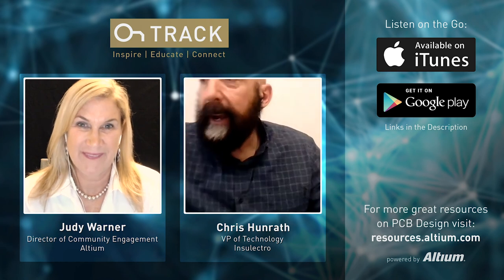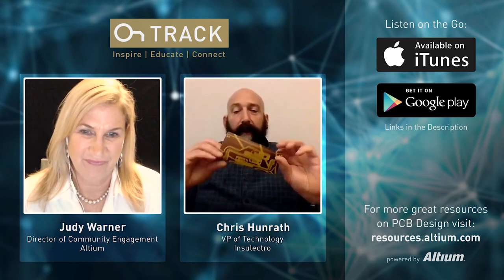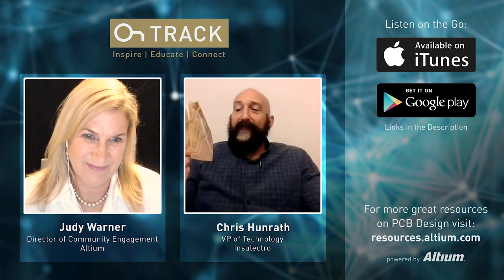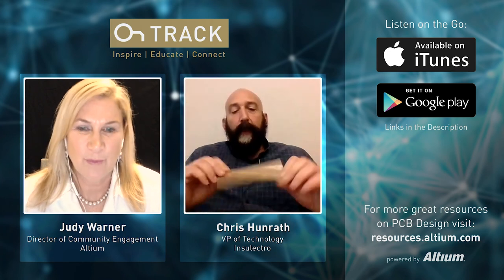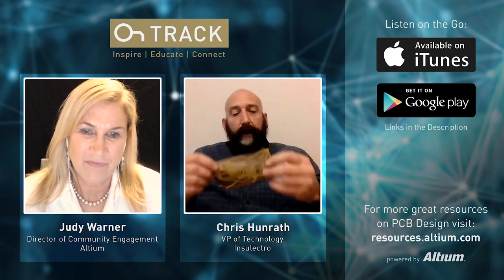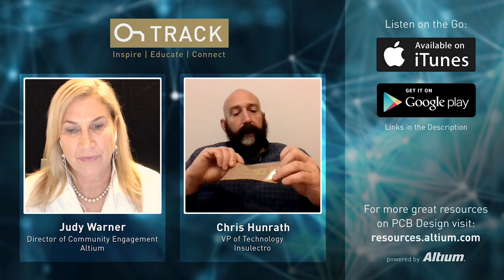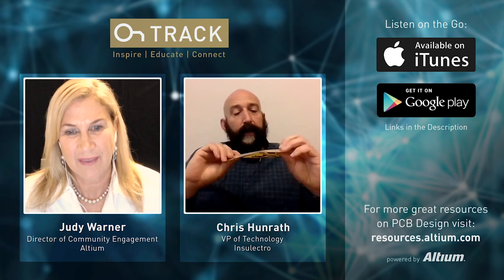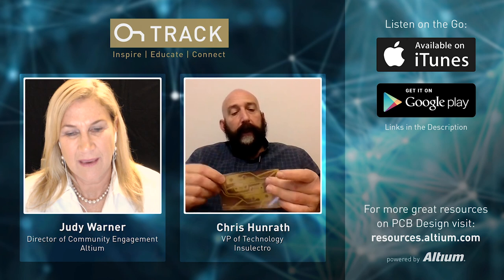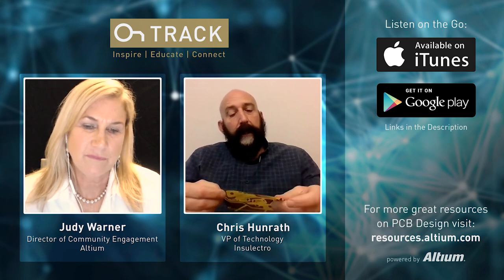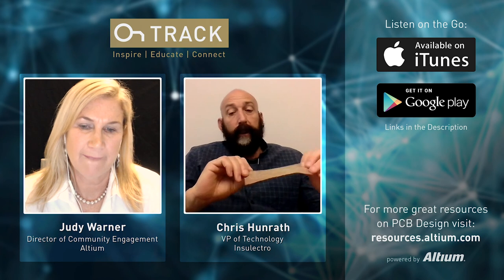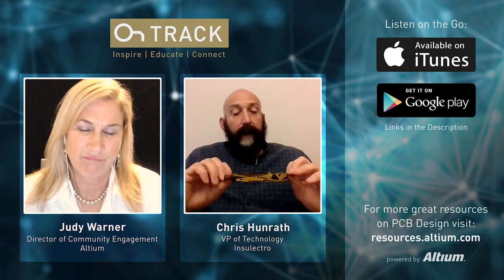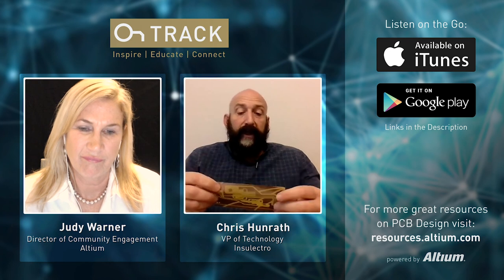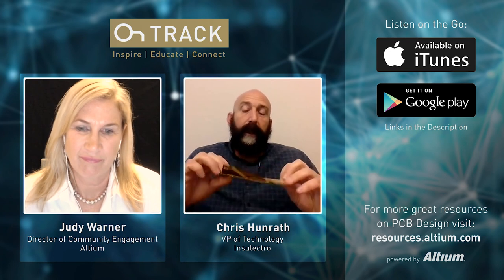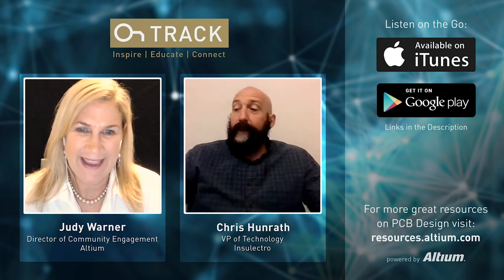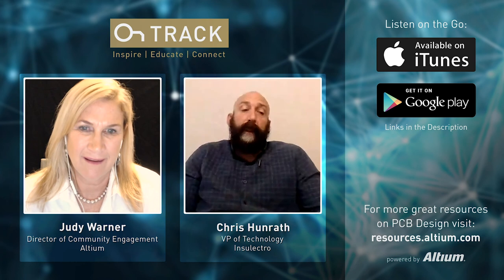Anyways, I actually have a board here. Okay. Let's see it. Unfortunately it's single-sided, so it's kind of like a potato chip, because there's only one layer of copper and only one layer of prepreg. But this is actually DuPont's AP product with Isola Tachyon prepreg. And it's a spread glass prepreg. So you have the spread glass prepreg on one side, and you've got the Pyralux AP on the other. So you minimize how much glass is in here, which really drops the amount of micro Dk effect, which would lead to skew and other signal performance issues. So there are lots of different ways you could use the flex materials, even in a rigid design.